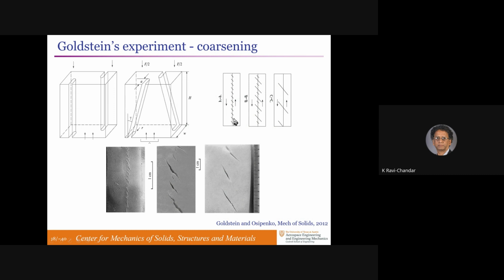And here's a cartoon of what the daughter cracks look like. The background parent crack is along that line. The daughter cracks are tilted, and there's a spacing between them. He did these experiments in Gruyere cheese so that it's easier to slice them and see what the daughter crack geometry looks like. So at state A, when the cracks had just started from the parent crack, there was a spacing of those cracks that you can see here.